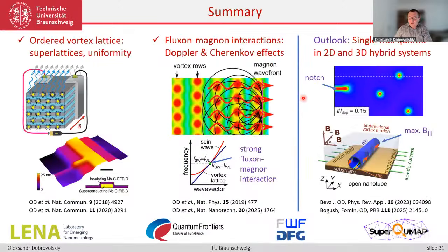This brings me to a summary of my presentation. There was quite a set of works devoted to the optimization of ordered vortex lattices, which could be achieved, for instance, by having periodic antennas, periodic intrinsic structures, in order to get sufficiently uniform vortex lattices. The approach which worked best is to have a superconductor in the dirty limit, but still quite uniform, and supporting vortex velocities of the order of 10 kilometers per second. And then, in addition to, for instance, the Doppler effect in the regime of low velocities, in the regime of high velocities it was possible to excite spin waves by using a Cherenkov-like regime of radiation.